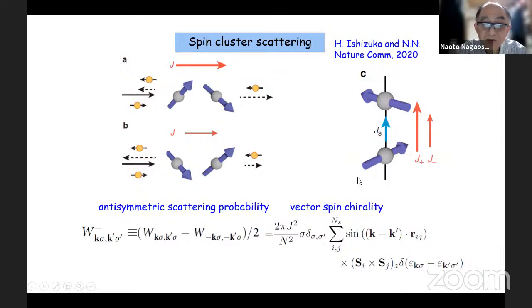So this can be understood rather easily in the following way. As I mentioned in the multiferroic story, this tilted spin or vector spin chirality leads to the spin current between the two sides, right? So this spin current and the conduction electron current can interact with each other, because this is a scatterer. So then this J up and J down will scatter with a different probability in the presence of the spin supercurrent between the two spins. So that is the interpretation for this formula. But in any case, we have this expression for the scattering probability.